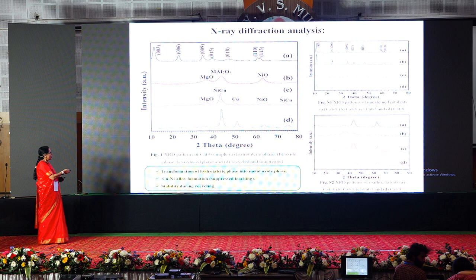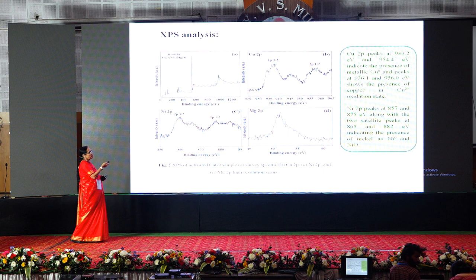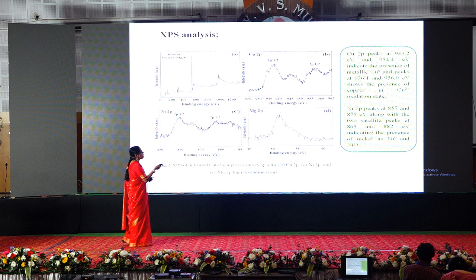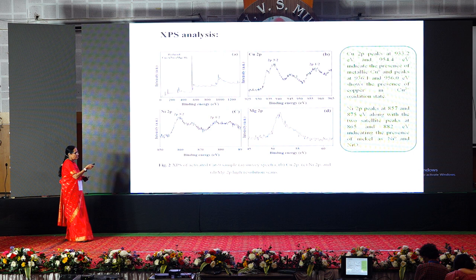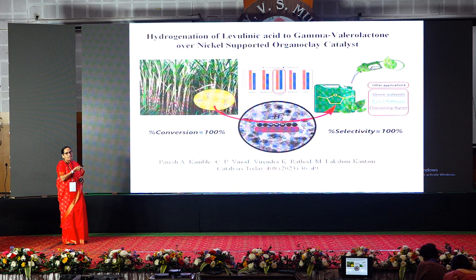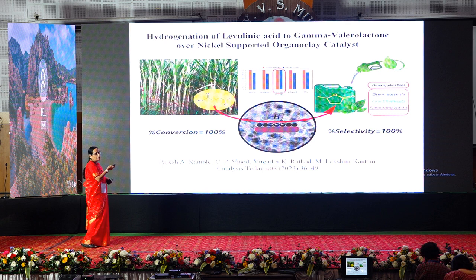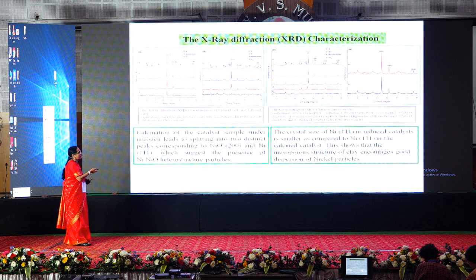And also we did the XPS analysis to show the oxidation state of the metals. You can see the copper is in the 2+ oxidation state, and nickel exists as nickel 0 and nickel oxide. We completely characterized the catalyst, and we did the reaction. And similarly, you can also do levulinic acid to valerolactone with another catalyst we made, a nickel supported on organoclay catalyst. Again, we have completely characterized the catalyst and we did the reaction.